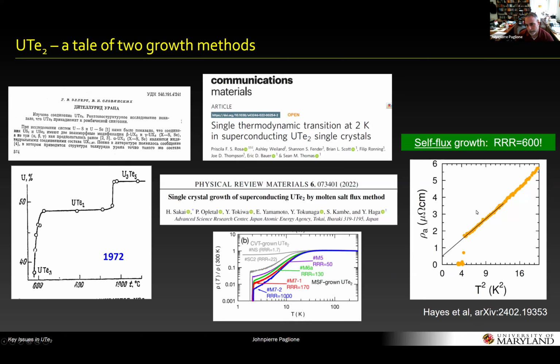I also note right here, and I'll get back to this later in the talk, that the magical molten salt flux is great. It's a great development by the Haga group. But in fact, you can grow crystals with a self flux, which is just tellurium, and get superconducting samples. So actually, we first reported that in this recent paper on thermal conductivity. So molten salt is nothing special. It's just a way to control the stoichiometry that you need to get superconducting crystals that reach up to about 2.1 Kelvin. Okay.